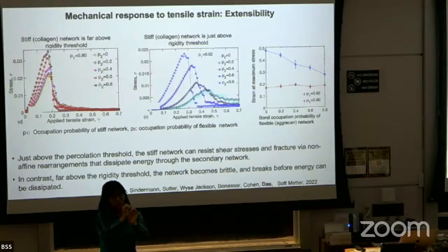Because the stress is quite concentrated. In a double network, the second network helps to redistribute the stress over larger areas. And if the second network is not very dense, it can undergo low-energy or non-affine deformations and movements that cost much less energy. But if your second network is quite dense, then you are suppressing these non-affine deformations. And once again, you're bringing the network to a situation where it can only relax this accumulated stress by breaking or buckling of bonds. So if you add too much material to the second network, you are suppressing these non-affine deformations, and it will start breaking at lower strains.